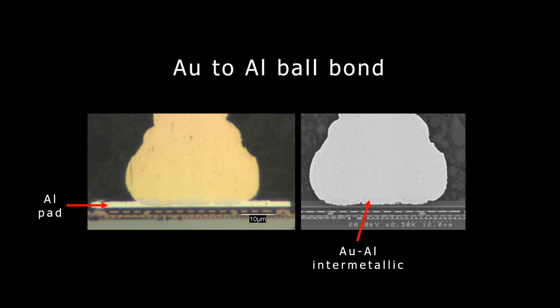This is a cross-section of a good ball bond. The left image is optical and the right is a scanning electron microscope image. During the thermosonic bonding of the gold bond wire to the aluminum pad, the two metals mix and form a thin intermetallic region.